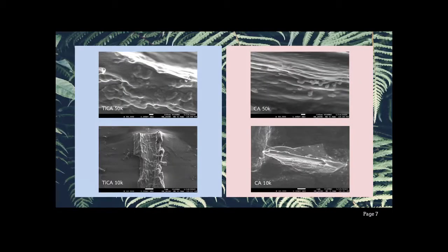These are the pictures from SEM under 50,000 and 10,000 times magnification. All of these show that the structure of doped aerogel is rougher than the other one. With more magnification, we can predict that titanium dioxide is attached on the surface, creating a cauliflower-like surface.